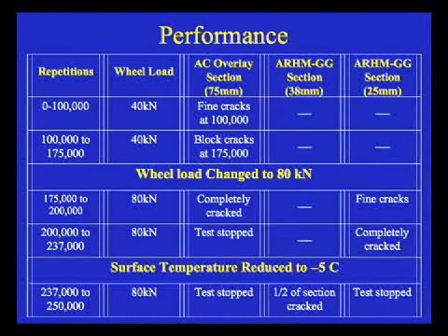The conventional section failed at 175,000 repetitions, and that was the design life. According to the Caltrans overlay design, it predicted 172,000 to failure. Well, it was pretty close here, so we felt good about how this was going. We then went to the half section. We got up to 175,000 with no cracking. So we doubled the wheel load, no cracking, no cracking. What are we going to do now? We're running out of time.